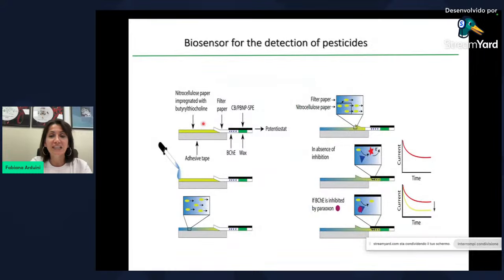So this is exactly what happens when we make the measurement. We add the distilled water to the strip preloaded with the enzymatic substrate. So the enzymatic substrate flows through the electrochemical cell in which the enzyme is entrapped. So we have the enzymatic reaction, which produces thiocholine, which is detected at the electrode surface modified with Prussian blue and carbon black nanocomposite.